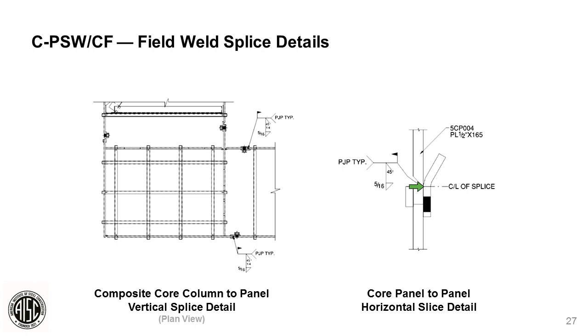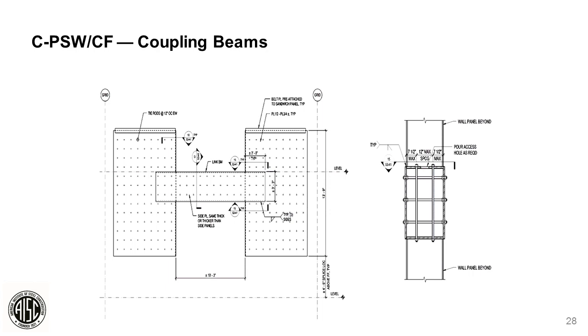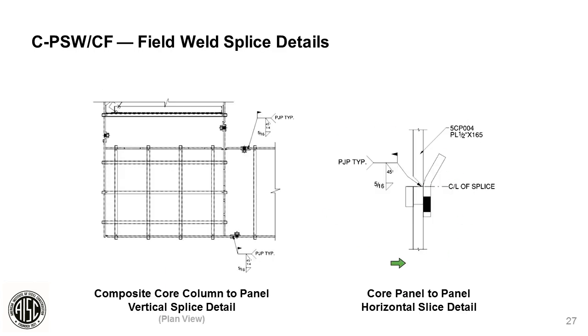If we call that a CJP there's really no way to get to the inside of that wall and do any sort of repair. So rather than worrying about that, we did a PJP with the reinforcing fillet. That same weld was utilized on the vertical surfaces as well, as you can see here. Again, I'll go back one more here, but again, given the size of Rainier Square, there's about 36 miles of this weld in the field to perform. So again, this was suited very well for the Seattle market where this particular erector and fabricator had the knowledge and the team to be able to pull that off.